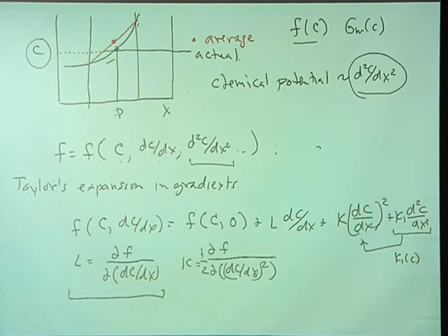And there's a relatively controversial issue in the community about why, as you'll see in a second tomorrow, the linear theory for spinodal decomposition has never been seen in metals, where it has been in polymers. One reason that people think is the case is that in metals this interaction range is so short, whereas in polymers it's so large that it's behaving more like a quote-unquote mean field model.